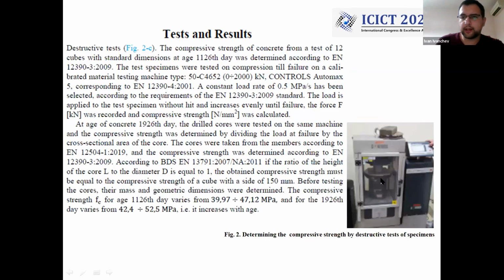About the cores and the cubes, you can see the testing machine. They are tested on a testing machine, a Controls Automax 5, corresponding to EN 12390. They are compressed till their failure, and the compressive strength is determined. So at age 1,126 days, the strength is ranging from 40 to 47.1 megapascals, and at age 1,926 days, varying